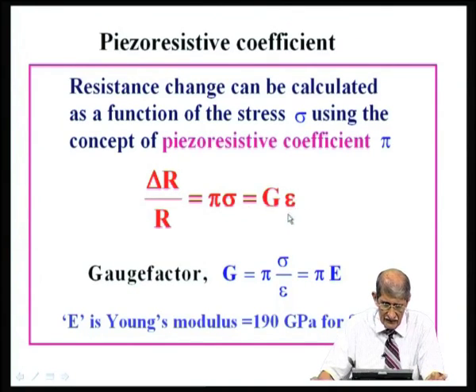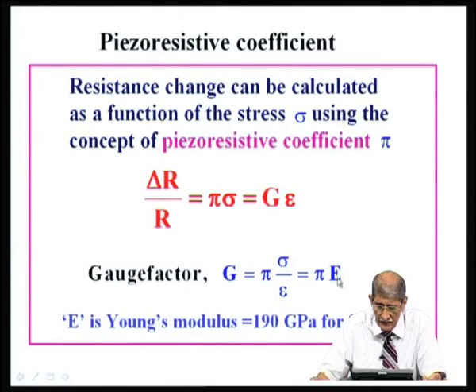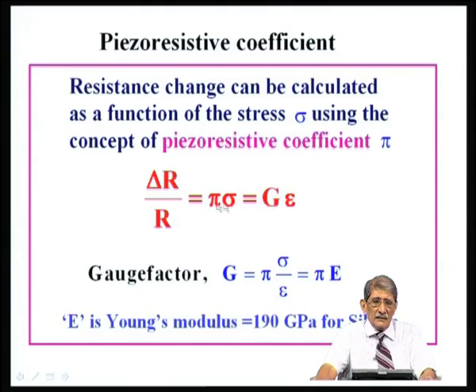Both are allowed. Okay. You can remember one of them, you can correlate, because sigma divided by strain, stress divided by strain, is called Young's modulus. In applied mechanics, all of us know that this is Young's modulus. So, gauge factor is related to the piezoresistive coefficient pi through the Young's modulus sigma by epsilon, and Young's modulus is usually defined by the symbol E. Do not confuse with the electric field, but this is a general symbol that is used, E. So, the gauge factor is related to the piezoresistive coefficient through the Young's modulus. Okay. But without confusion, delta R by R is piezoresistive coefficient into stress, or delta R by R is gauge factor into strain. The Young's modulus is about 190 gigapascal for silicon.